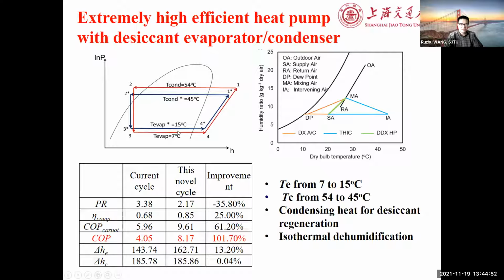And also now for the heat pump, there are other researchers trying to replace the normal air conditioning system with evaporation temperature 15 degrees centigrade and condensing temperature 45, because originally it is 7 degrees and 54. This is the Chinese standard. And you need 7 degrees for dehumidification, but now we use evaporation temperature 15, with dehumidification by the solid desiccant. And the condensing temperature is reduced because the solid desiccant heat exchanger, originally used as the evaporator, is stored with adsorbent water moisture. So you need the condensation for the desorption. In this case, it's like an evaporative condenser.